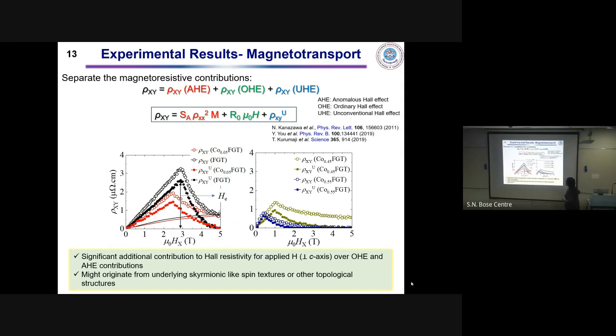This is the experimental value that we have observed of the transverse Hall resistance. Now, if I separate out these two contributions, which go like this in this case, we could see that there is an additional contribution to the transverse Hall resistivity, which is this full circled one. That is observed for Fe3GeTe2 and all the doped compounds. We could see a significant additional contribution to the Hall resistivity when the magnetic field is applied perpendicular to the c-axis, over the ordinary Hall effect and the anomalous Hall effect contributions, and this might be originating from underlying skyrmion-like textures in our system.